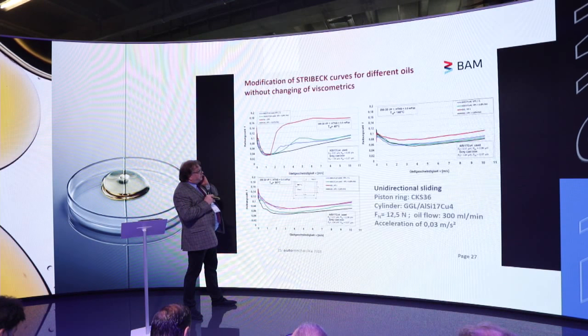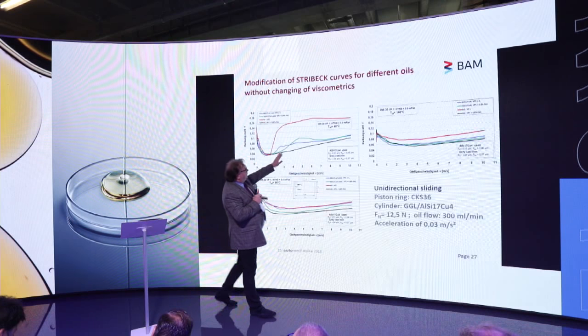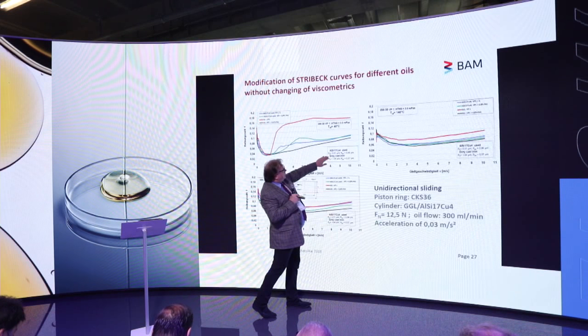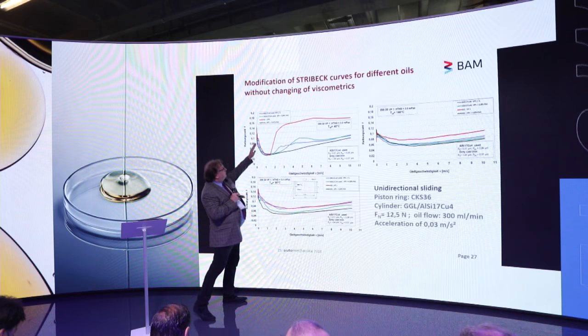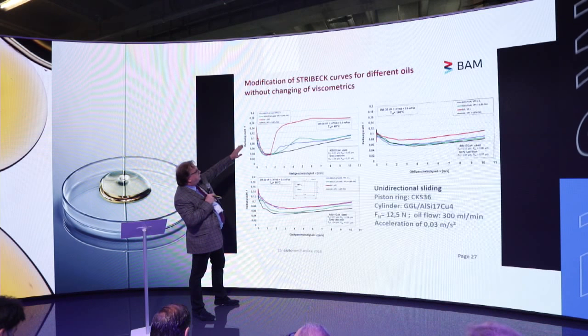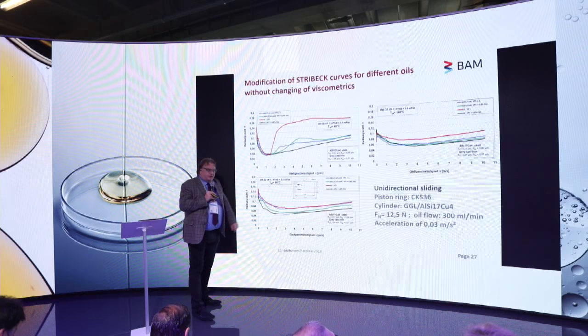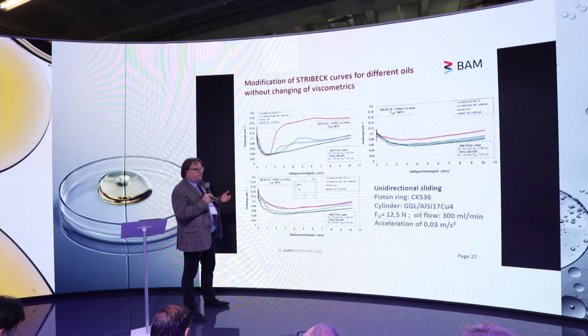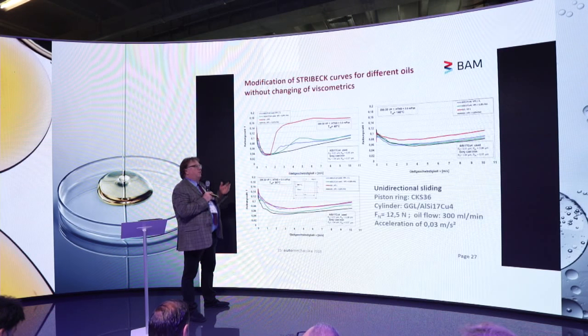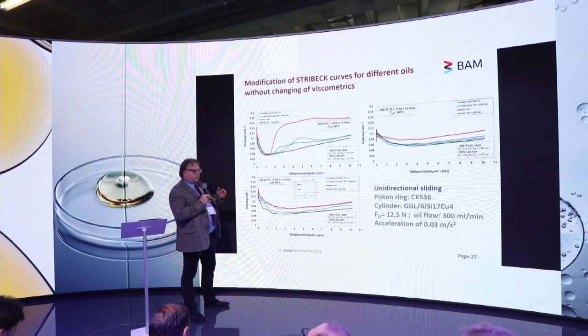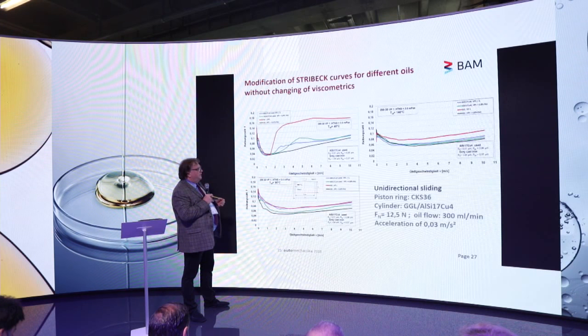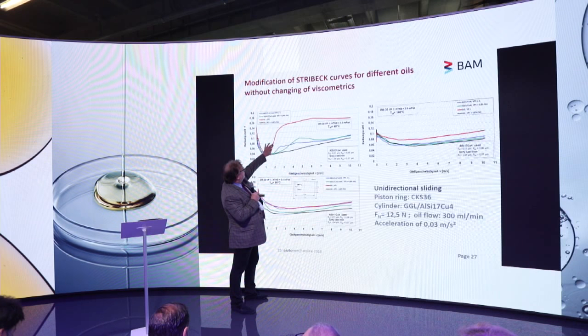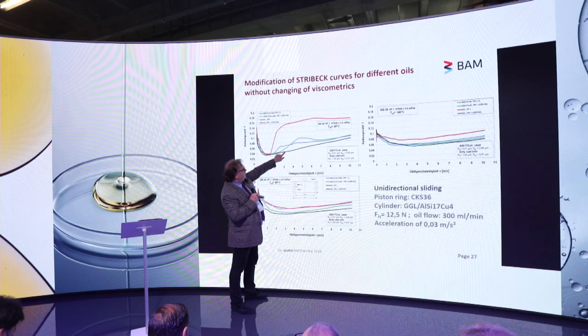Here you see the comparison between aluminum and gray cast iron, the factory fill oil without and with this additive. So it works for both. It is difficult to have a solution which only works for cast iron or for aluminum. It's good to have a solution which works in all types of cylinder liner concept. So you see here the red, you put the additive in, it goes down. Here's a big effect.